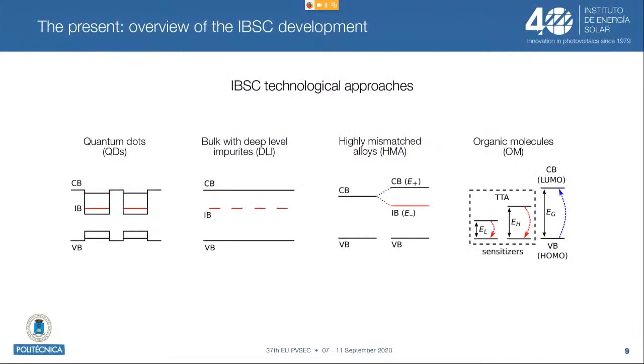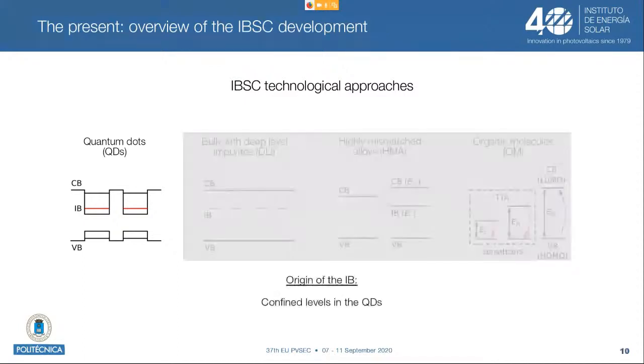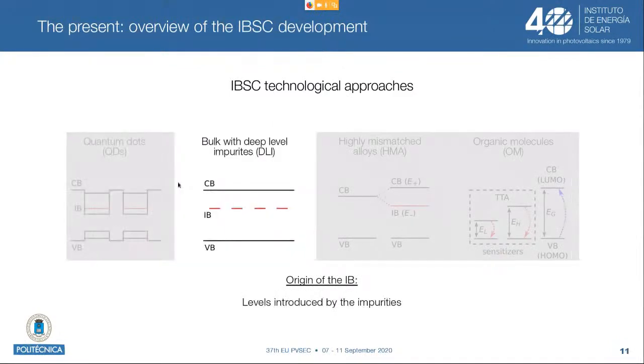So I was saying that there are four ways of implementing the intermediate band solar cell. Quantum dots were the first one proposed, where the intermediate band stems from confined levels in the quantum dots. So I'm drawing red lines here. Another one is to use impurities that introduce deep levels inside the bulk semiconductor, and these deep levels would play the role of the intermediate band.